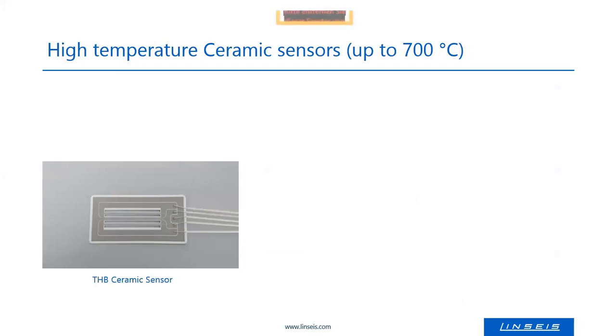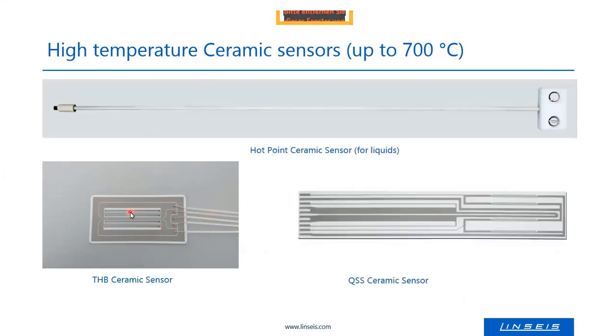For higher temperatures, we have ceramic sensors. The layout is the same, but the matrix is not Kapton, not a plastic material. It's a ceramic material. We have the classical THB sensor, the QSS sensor, and also a ceramic hot point sensor. And this ceramic hot point sensor is also very good for liquids because it has a low heating current, and the convection during the measurement in a liquid is quite low. So it's quite suitable to measure liquids as well, but we will see later on.